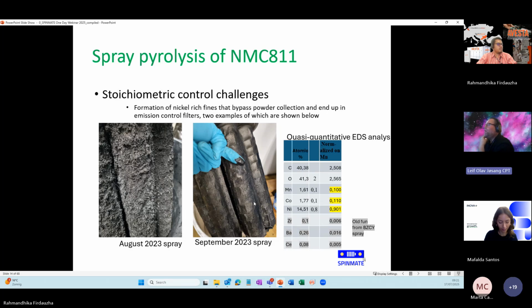We later found, or IREC discovered, that we were missing some nickel. So we checked the content of our filters, the powder that is not collected, and we found that that was quite nickel enriched. You can see there's some barium and zirconia there as well. That's old fun from a previous production of proton conducting material. So there's a tiny amount of that still left in the filter.